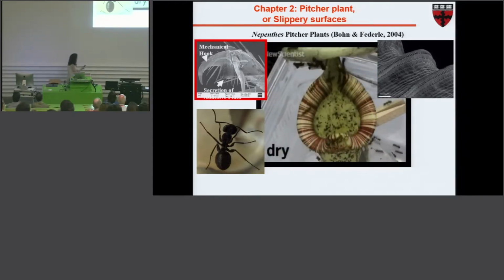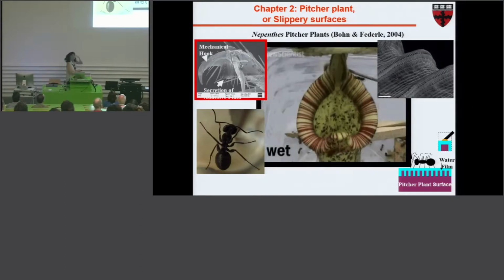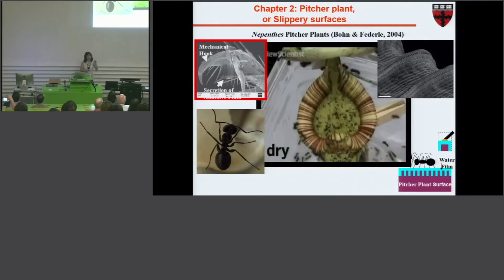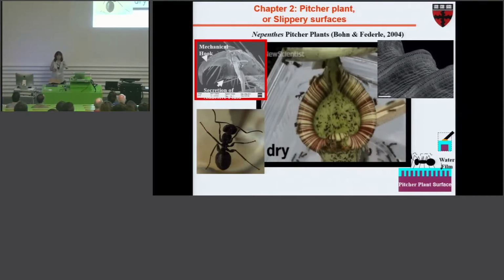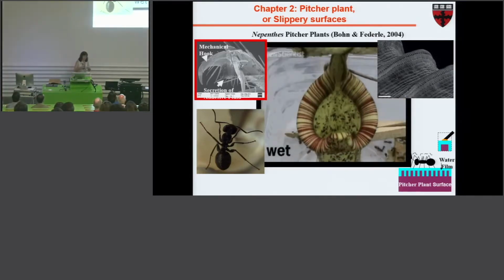So on a dry day, these ants experience the structured surface, they run around nicely. But on a wet day, since the surface is hydrophilic and structured, it means it's superhydrophilic. So it picks up water, and now the ants that have these oily feet are never in contact with the solid itself. Contact angle hysteresis in this case would be determined by the interaction between the oily feet and the liquid, in this case the water layer. And liquid-liquid interactions, unless they have chemical interaction between them, but in this case it's oil and water, are pretty much non-existent, and the outcome is that these surfaces are highly slippery and the ants cannot stay on the surface.